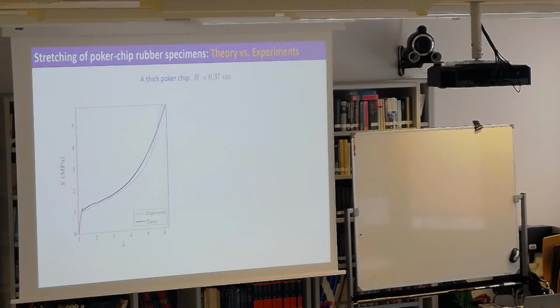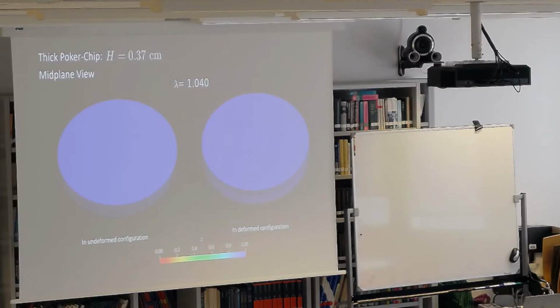Let me show you now a thicker specimen. Remember, when you make it thicker, you have fewer cracks, and the geometry is very different. This one is very thick. We only see a bump here, which suggests there is only one crack, and that is actually what happens in the experiment. So this is the simulation. Again, this is the midplane, undeformed. This is deformed. You're going to nucleate here in the middle. In the deformed configuration, it's going to look large because it's deformed, right? But it's nothing but a crack.